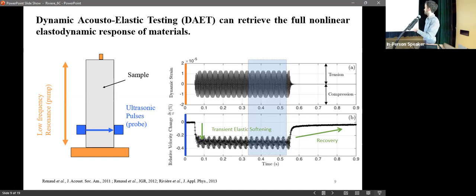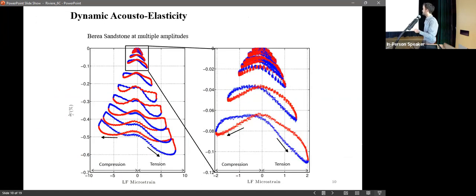All right, so now what we are going to do is to look at the changes in velocity as a function of strain. And we do that for multiple amplitudes of the pump. So we first vibrate with a tiny amplitude and then with a larger and larger amplitude. And this is how we get these nonlinear signatures. This is an example in a Berea sandstone. We plot the changes in velocity as a function of strain. When the strain is positive, we are in tension. When the strain is negative, we're in compression. What we see is that as we increase the pump amplitude, the velocity drops on average. So that's related to parameter alpha coming from this hysteretic nonlinearity that I mentioned before.